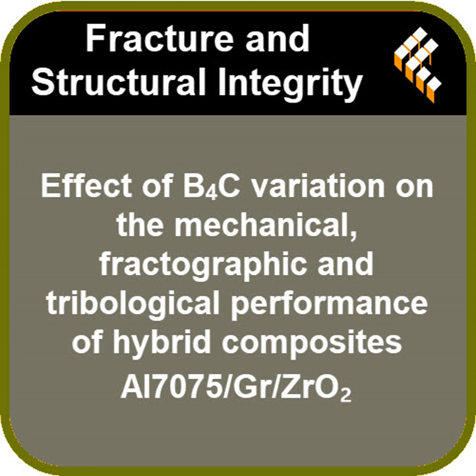Does that compromise its safety factor in something like a crash structure where you need impact absorption? That is the critical question. And it confirms the fracture mode shifted from a classic sort of stretchy ductile failure to what's called a quasi-brittle failure. It just means engineers have to account for a slightly shorter yield to failure window. I see. But for static parts or high compression environments, the huge increase in load capacity far outweighs that small reduction in flexibility.